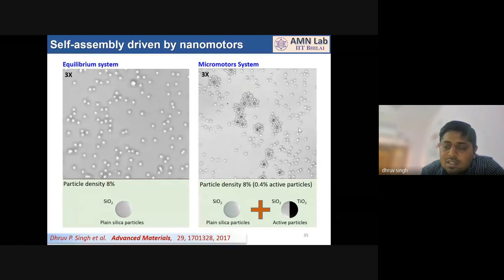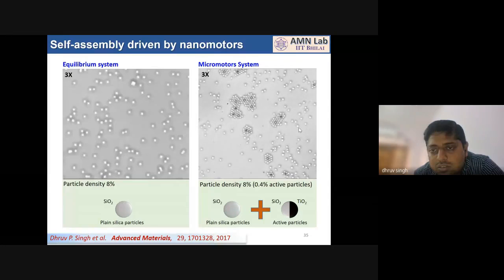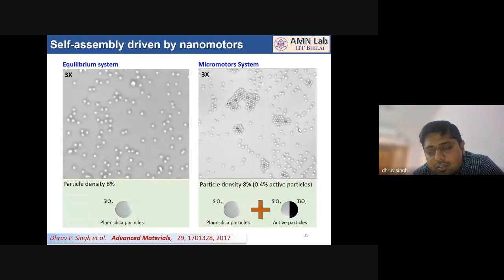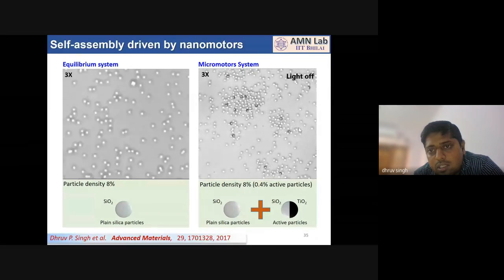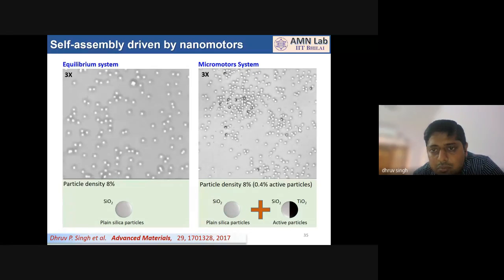And interestingly, this whole activity survives only until the light is turned off. Then when you turn off the light, the whole activity melts down and the particles go back to their original Brownian state. So this is an interesting observation. It shows the formation of reversible crystals in a colloidal system without taking care of critical particle density and in a very rapid manner. This whole activity here took less than 3 minutes, which was going to take forever in the equilibrium system without a nanomotor or micromotor system. So micromotors are very useful here. They help in forming reversible or reconfigurable crystals.